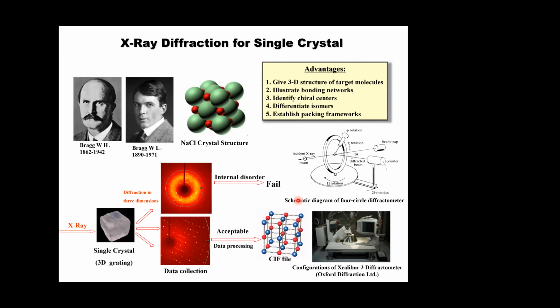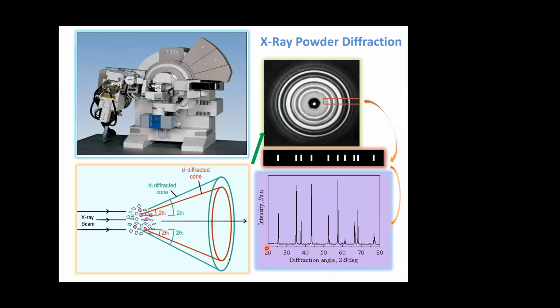Then we look at one technique that was invented a long time ago. We call it X-ray diffraction. At the very beginning, X-ray diffraction meant you basically have the X-ray shooting at your material, and the X-ray goes through the crystal structure. And then from the diffraction pattern, you make judgments on what the crystal structure is, and then you know what kind of mineral you have. So this is the so-called three-dimensional X-ray diffraction of a single crystal. But a lot of the time, particularly in the environmental field, you will not necessarily get a single crystal material. So what you're getting will be powder.